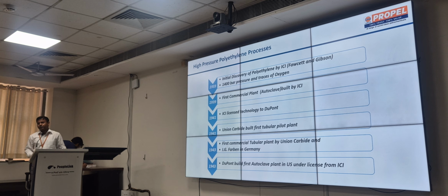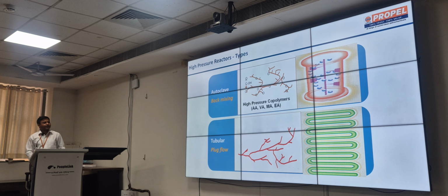The difference between autoclave and tubular is that autoclave gives a broader molecular weight distribution than tubular. For applications like extrusion coating, where neck-in is the major concern and the coating thickness is around 6 to 8 GSM, autoclave grades, produced through the autoclave LDPE process, have better performance than tubular grades. The first commercial tubular plant was by Union Carbide, and DuPont built the first autoclave plant in the US under license from ICI.